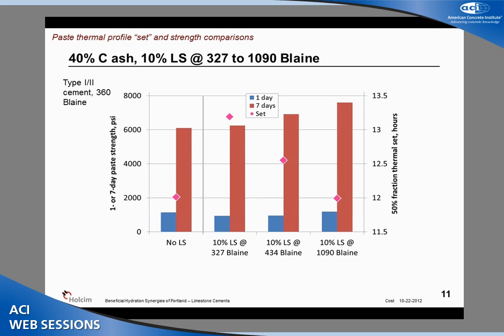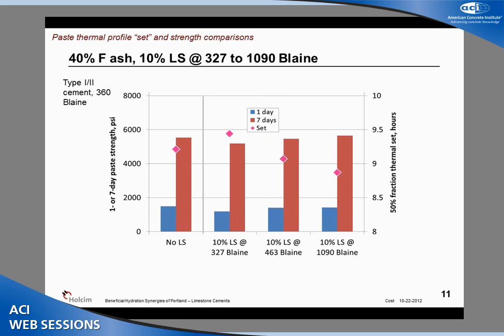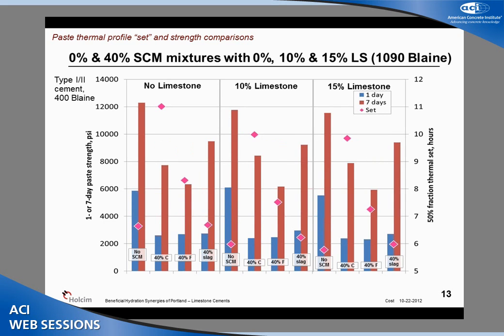Notice the strength trends, both early and both 1 and 7 day strengths. Very interesting strength enhancement as we get the limestone finer and finer. We believe this to be associated with the aluminate interaction with the calcium carbonate. Class F fly ash is a little bit less interesting with respect to strength, but you do see the enhanced setting times similar to the ordinary Portland cement alone.